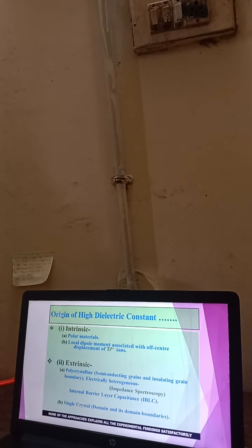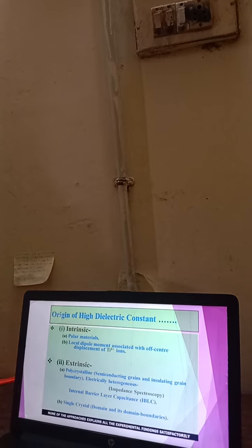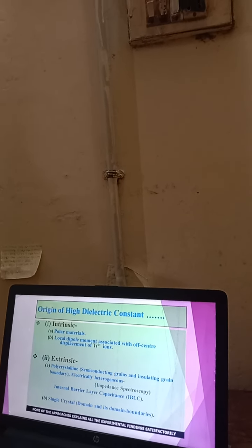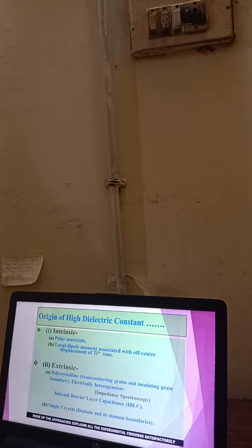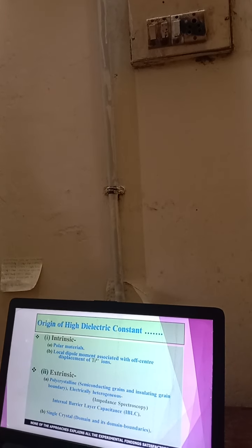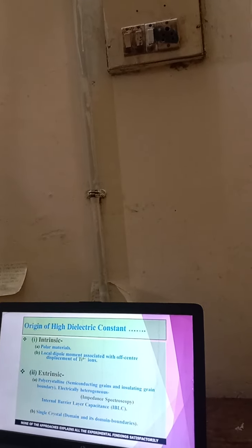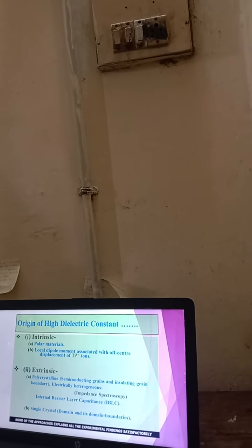In extrinsic, it is also divided into two parts. First is polycrystalline, meaning the material should be polycrystalline, that is, semiconducting grains and insulating grain boundaries, and electrically heterogeneous. Internal barrier layer capacitance is responsible for the high dielectric constant. Second is single crystal domains and their domain boundaries.